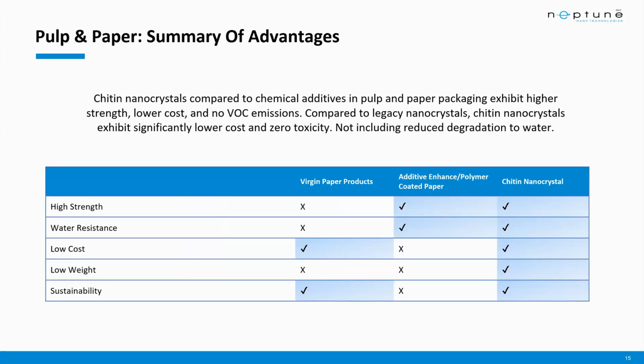So as a quick summary, we see a lot of potential of chitin nanocrystal for paper packaging applications, both as an in-pulp additive and as a coating. We see advantages in strength, toughness, barrier, antibacterial activity, as well as flame retardancy. But most importantly, chitin nanocrystal is a naturally existing material that was simply processed into a nanocrystal form. So of course, this is fully sustainable as well.